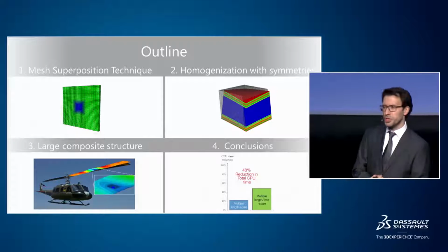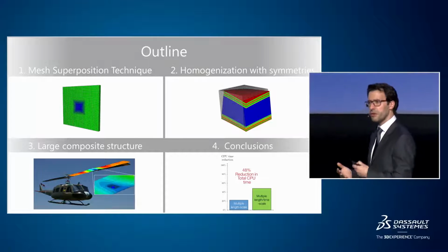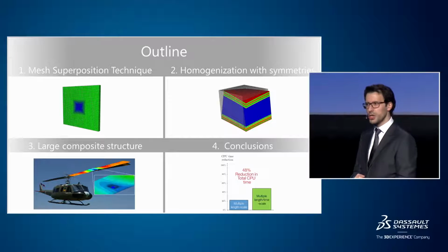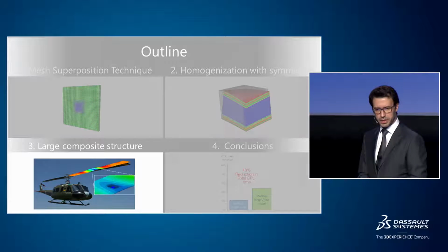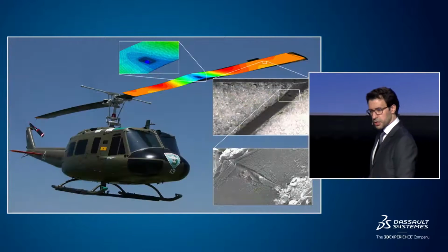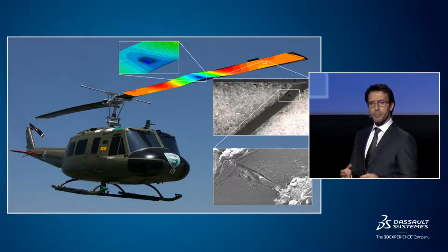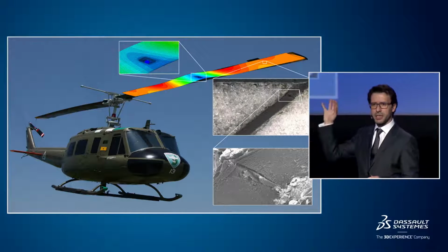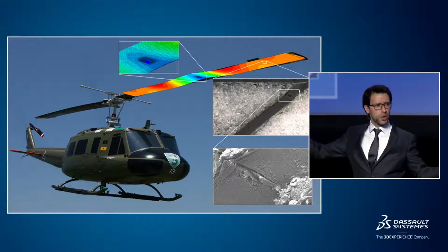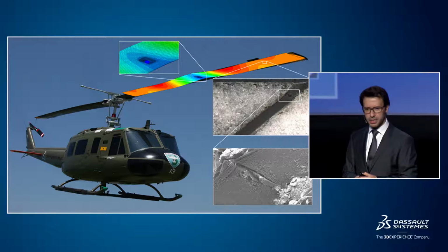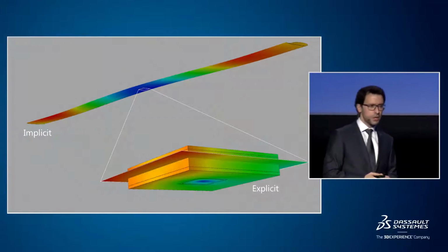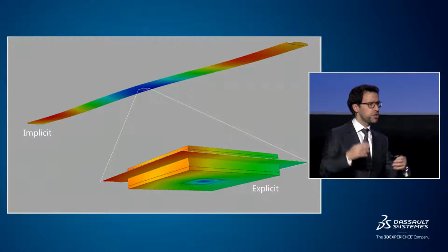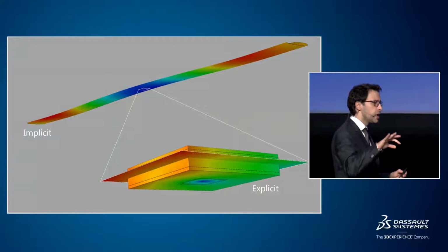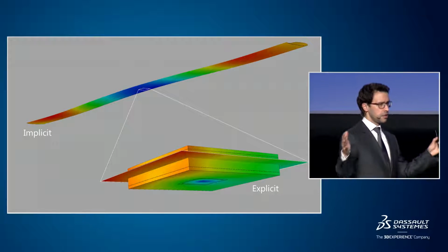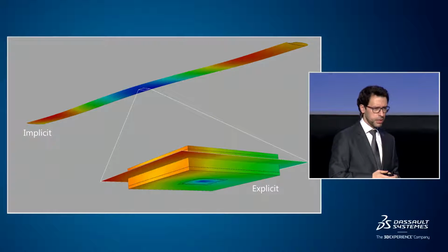And now I want to return to this simulation of a large composite structure using these techniques. So this was our helicopter. Remember, we have failure of pins close to the impact region, and we are trying to simulate a very large sandwich structure. So this is our model. You can see on top the implicit part of it, which is most of the model, and on the bottom a refined region which is modeled in explicit.